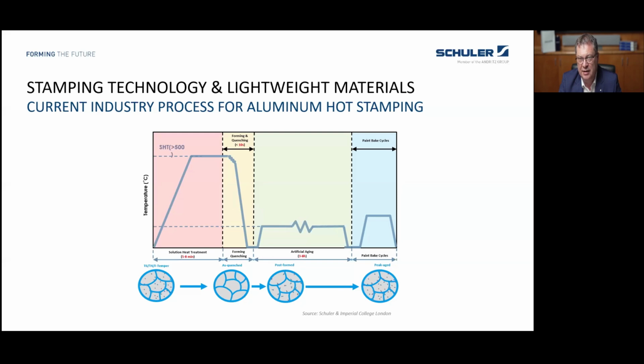And during that time, you face the effect of solution heat treatment. What's that? That means that the precipitations in the aluminum microstructure, which are responsible for the hardness of the material, will go away during solution heat treatment. That means the material is very soft when you take the blank out of the furnace. Then you can perfectly form it, and then you quench it down, and then you have a perfectly formed part. But unfortunately, it lost all the precipitations and it's not hard anymore.